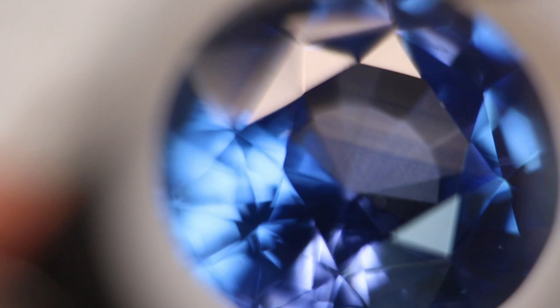Other things that I can see are that these needles are quite long, and that is very typical with the origin of Sri Lanka. Last but not least, I can see that these are fuzzy lines. The fuzzy blue lines give me a strong reason to believe that this stone was heat treated. These are the types of features we look for when using a microscope to evaluate if a stone has been heat treated or if it's completely natural.